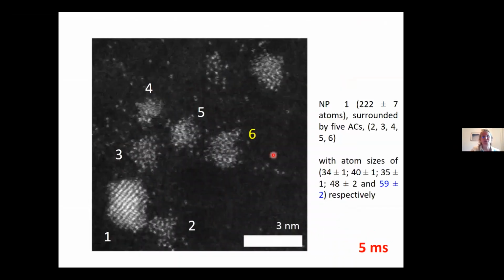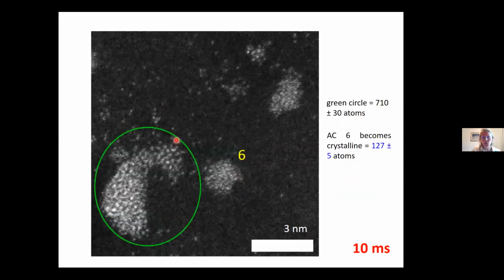When we saw these images, we were really amazed by them. Here you have a single nanoparticle. Here you have 5 amorphous clusters. The question is, can we predict what's going to happen? Are the amorphous clusters going to grow and get bigger? Are they going to disintegrate? If we follow this after 10 milliseconds of growth, you see that all of those amorphous clusters, and this one here, disintegrated into this nanoparticle.